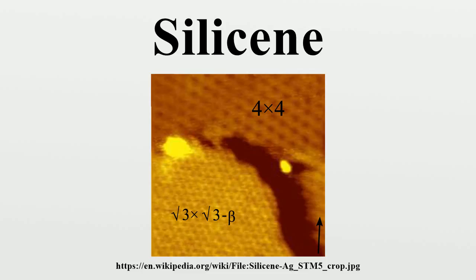These orbitals are close enough in energy to cause the distortion to low symmetry configurations of silicene. The buckled structure can be flattened by suppressing the PJT distortion by increasing the energy gap between the LUMO and HOMO. This can be done by adding a lithium ion.